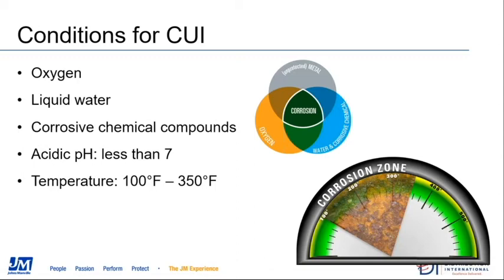For corrosion under insulation to occur, you need a combination of conditions to exist, as you can see in that little circular graphic image toward the center of this slide. Where you have the overlap of those conditions is what puts you in what they call the corrosion zone, or the opportunity for corrosion to occur. Those conditions include the presence of oxygen, water in the liquid form. Water vapor by itself will not initiate corrosion, but water vapor that makes it to a cold surface and condenses and then becomes liquid water can contribute to the opportunity for corrosion to occur.